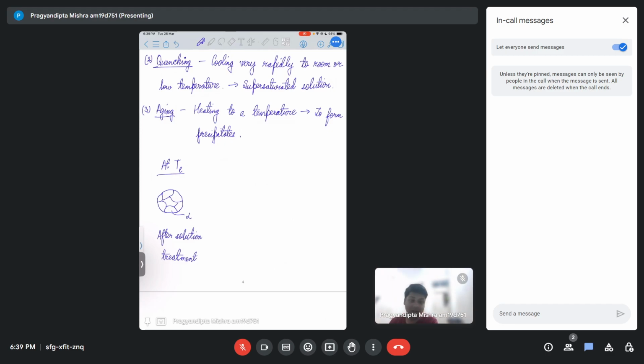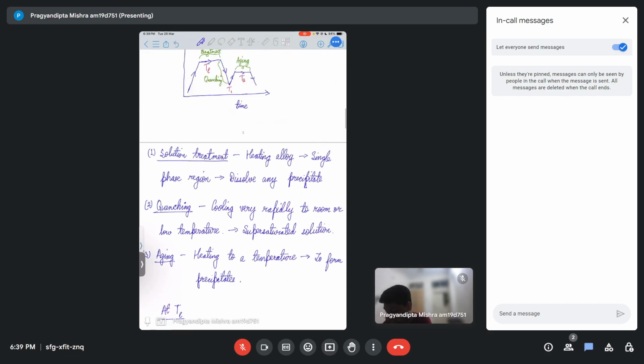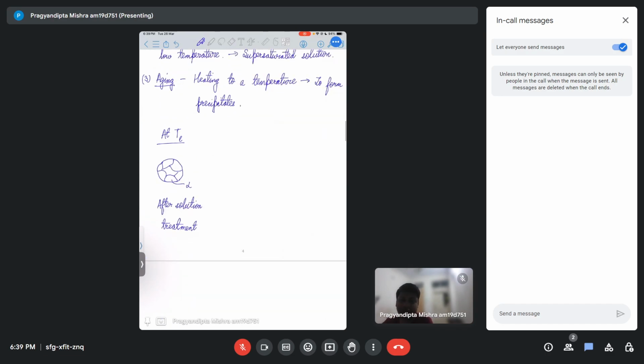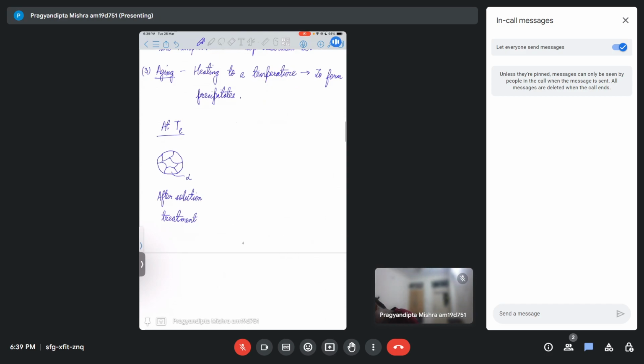Yeah, so coming back to the microstructure. This is after solution treatment, you will get a microstructure something like this. Now when you are at T1, basically you have just quenched it. You will get a supersaturated solution which will still not have precipitate. You will still have a similar kind of setup, you still have alpha phase, exactly the same as what we had before, after quenching, but this solution will be supersaturated.